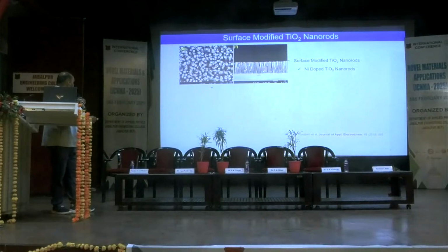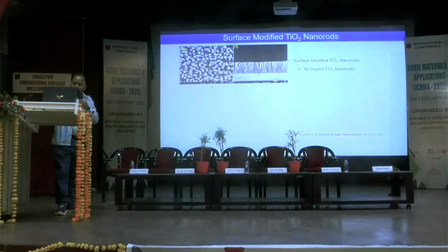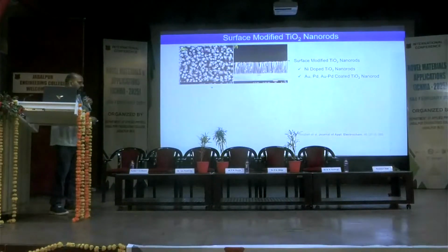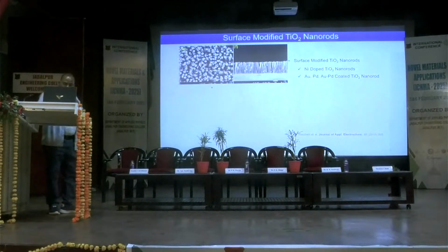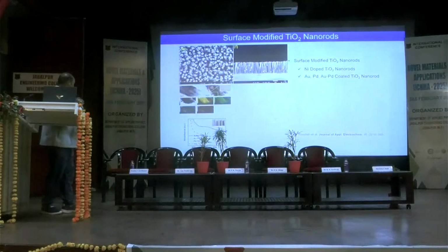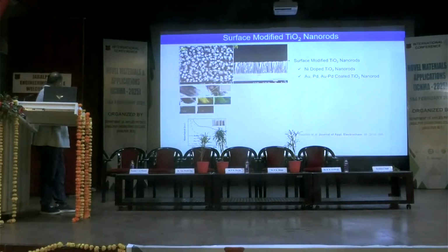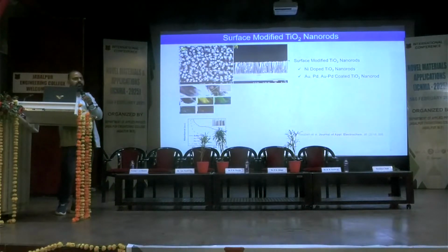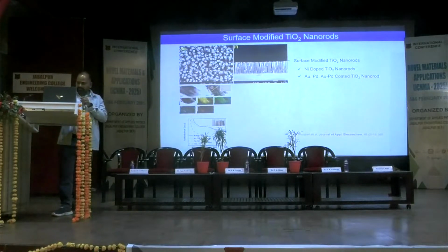We also doped the TiO2 surface with nickel. And then, again as I used in an earlier study, we coated with gold and palladium, and we developed these structures in another study. You can see here how the absorption profile changes when we modify with gold and palladium together. As I said, it's a wide band gap material, but it switched toward a visible light active material when we modified it with this metallic coating.